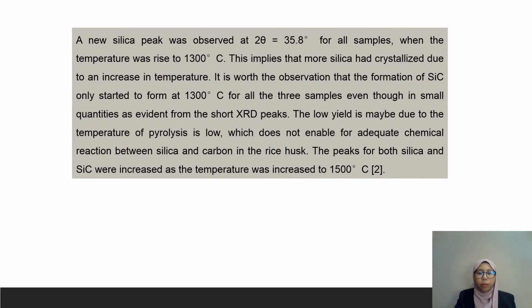This implies that more silica had crystallized due to an increase in temperature. It is worth the observation that the formation of SiC only started to form at 1300 degrees Celsius for all the three samples, even though in small quantities as evident from the short XRD peaks.